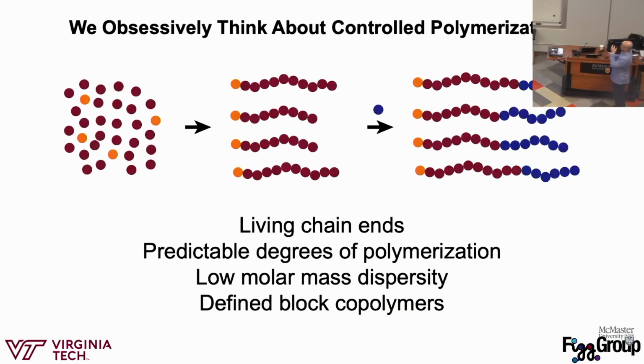And so what this means is if they grow at approximately the same rate and they start at the same time, you'll have this low molar mass dispersity because they're all growing at about the same rate. So you'll overall have the same average molecular weight. What's also really important is that you get these living chain ends. So after you do this polymerization, you have minimal termination events so that you could include, say, this blue monomer and make this block copolymer.